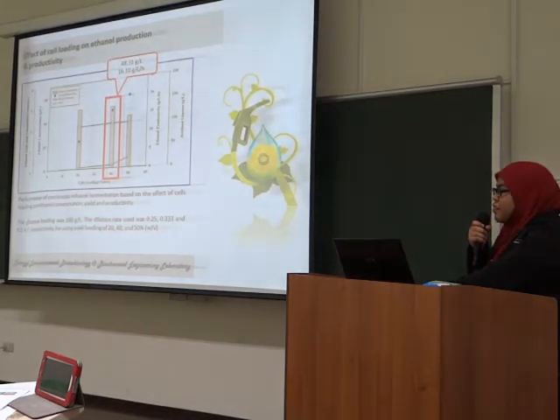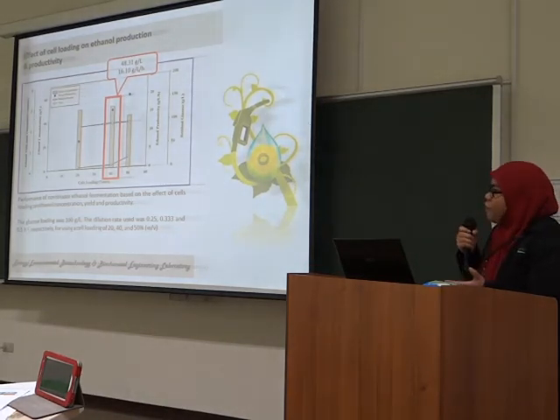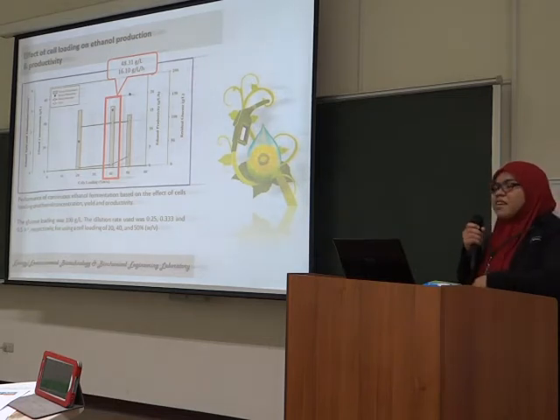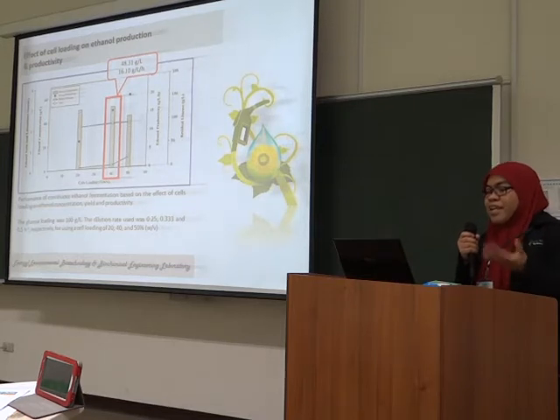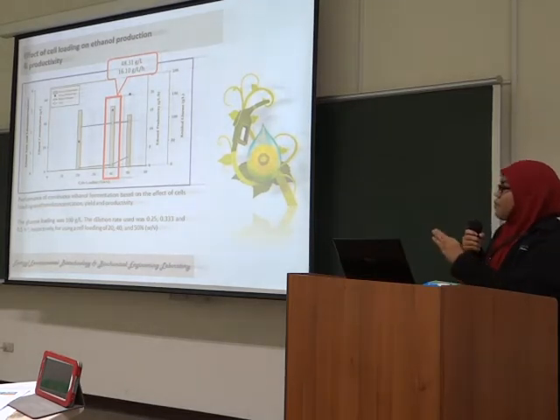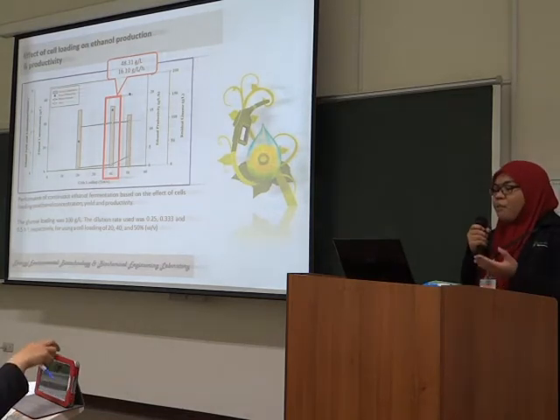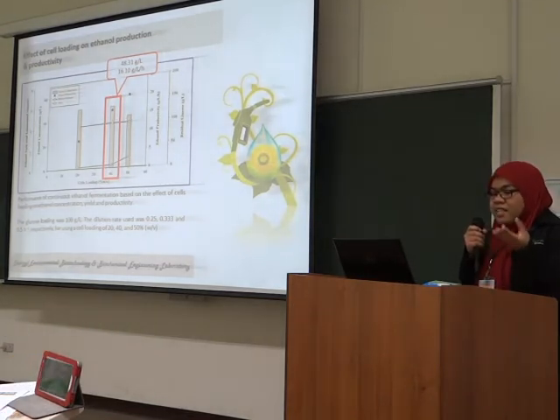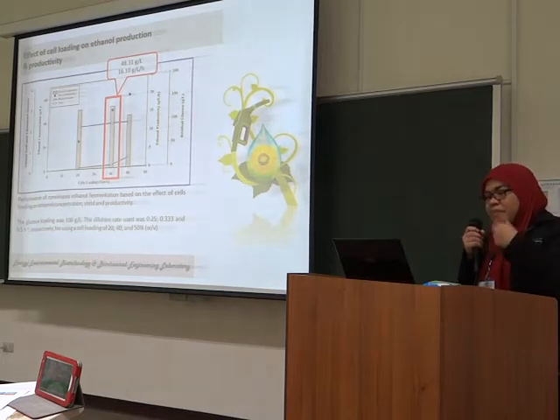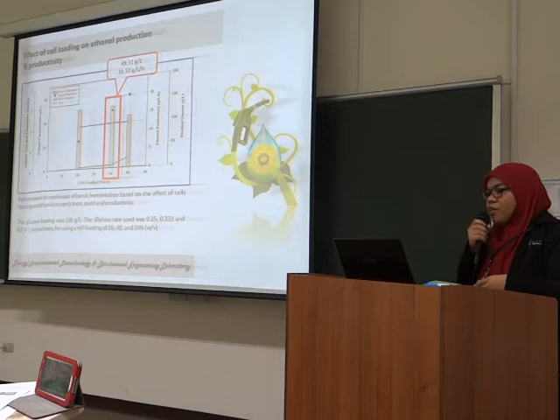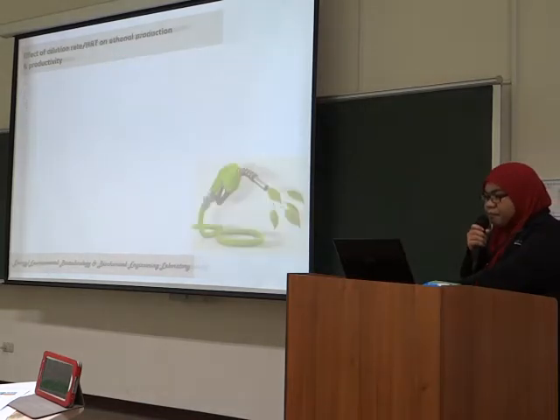Actually, normally with higher cell loading, it could produce more ethanol, but in here we have some problem, because when we try to load more cell, the cells tend to stick to each other. That makes mass transfer a little bit difficult. So we choose 40% as an optimum value.